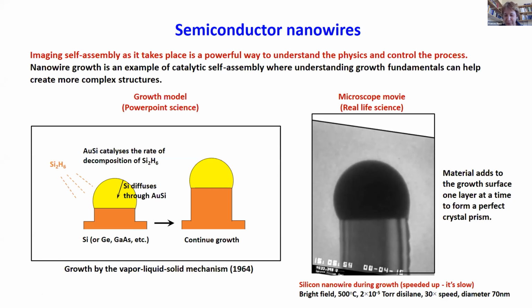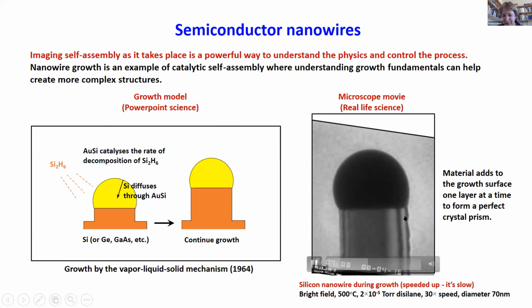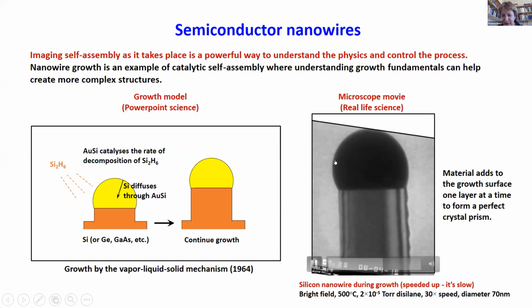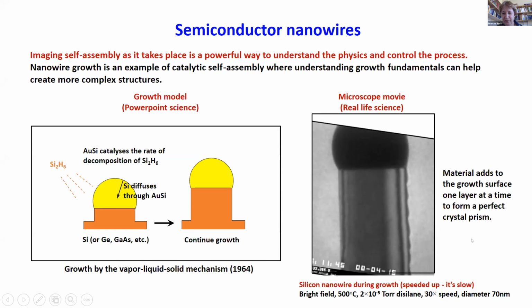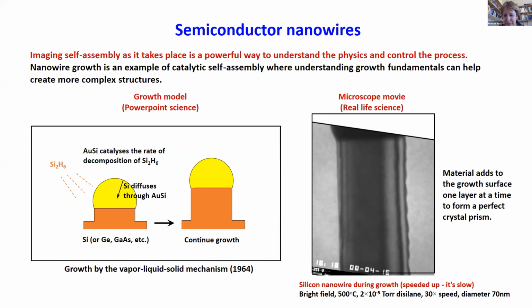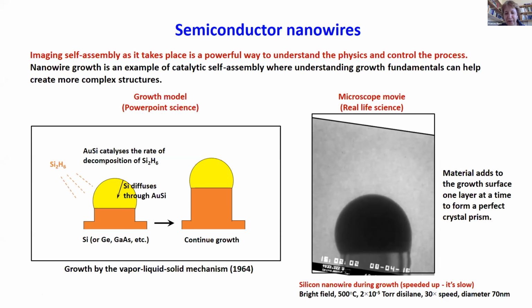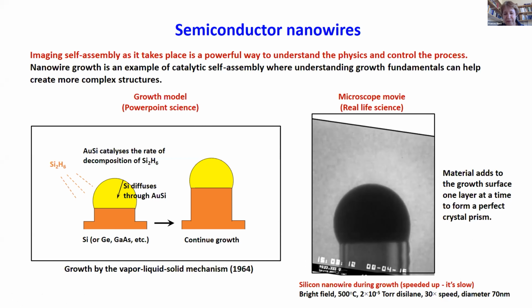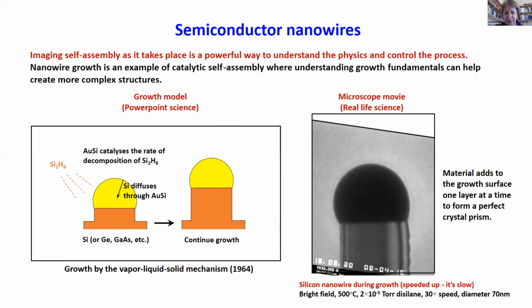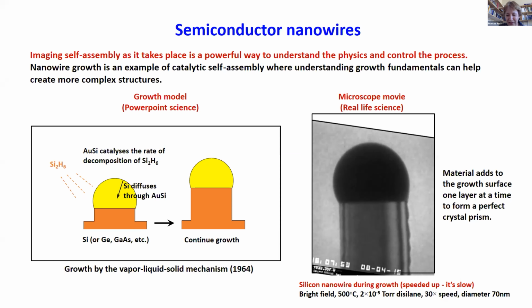So you can see a perfect prism of silicon is forming. Look at the thickness fringes here. You can see surface features. You can see the shape of the catalyst, the phase of the catalyst, the structure of the interface during growth. So this process was of great interest because of its potential for creating small structures. But again, as I said before, we want to understand the physics of this process if we're going to have a chance of using it in a real manufacturing context.